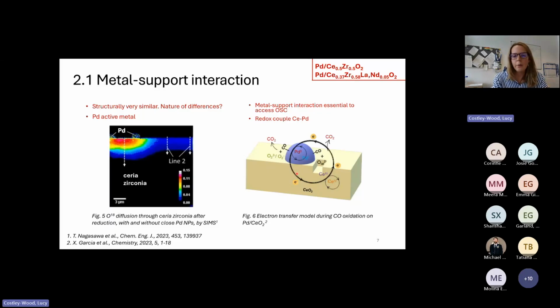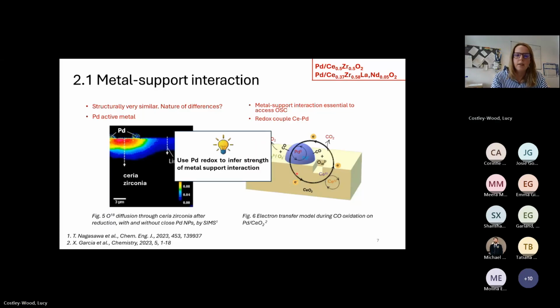So knowing how important this interface is and seeing the difference in conversion between our doped and undoped catalysts, we want to look into this more and see if this is the reason why the behavior is so different. And we figured that we can use this palladium redox mechanism to infer the strength of the metal support interaction.